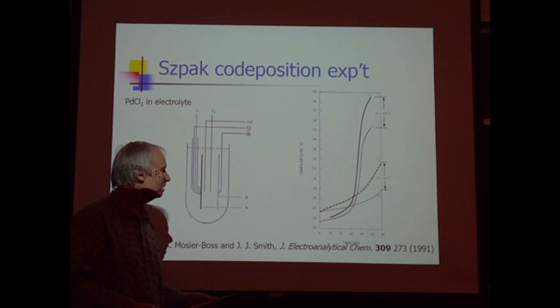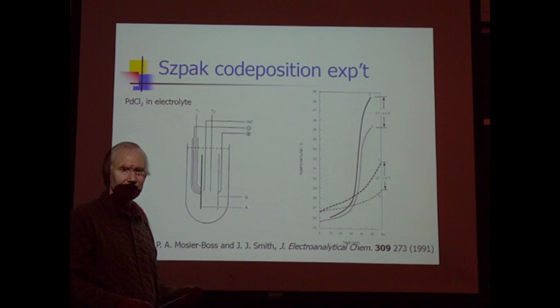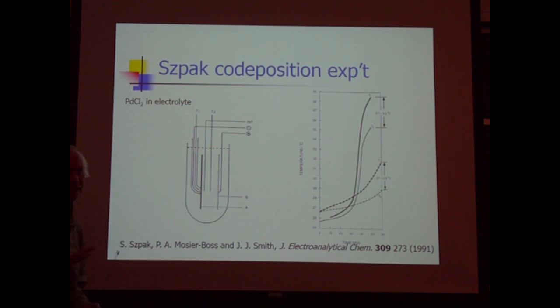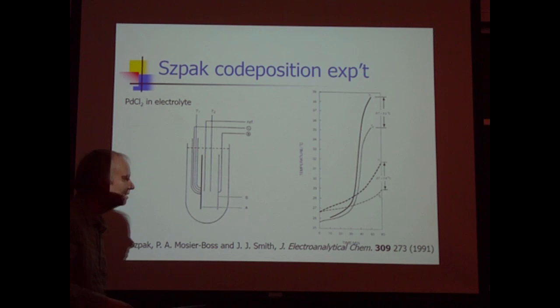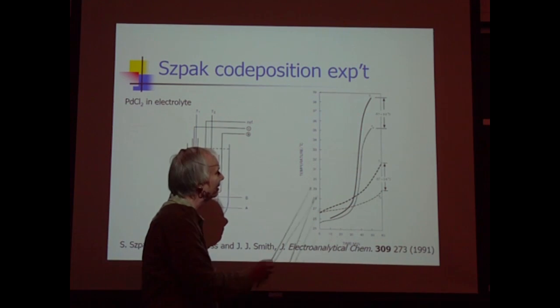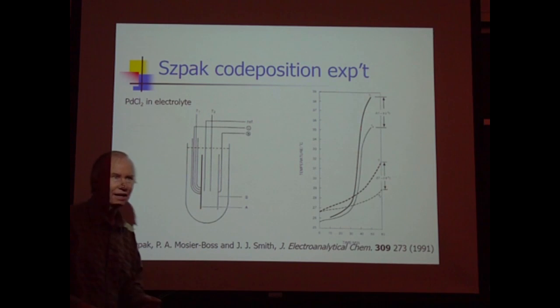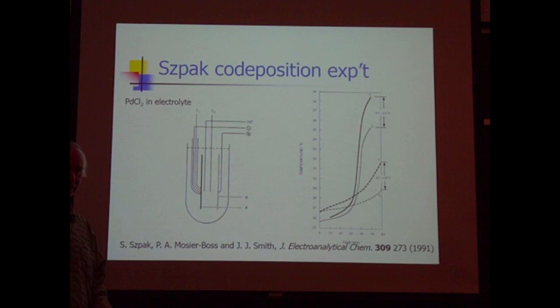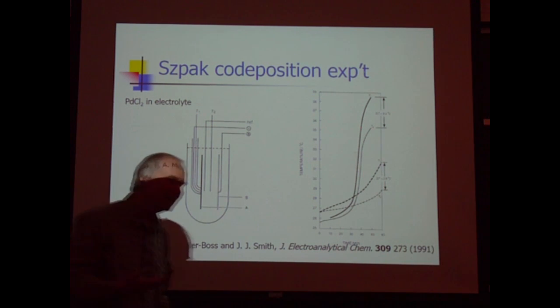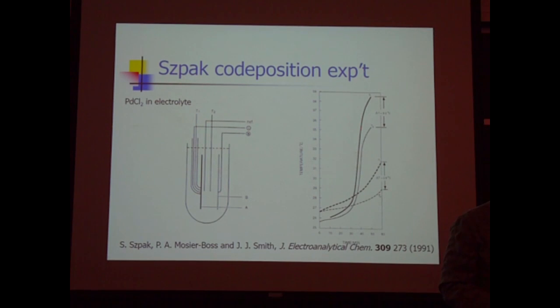However, we remarked on Monday that in the case of Fleischmann and Pons experiments and at the replications at SRI, you had to wait 3 weeks, a month, 6 weeks. You had to load, be gentle with your cathode, eventually raise the current, exercise your cathode. And it took something in the neighborhood of a month before you could see any excess heat. Well, here's Szpak's experiment. Here's time in minutes, here's 0, here's 60, and here's the temperature shooting up following co-deposition of palladium. So in the Szpak experiment, excess heat turns on very quickly. We noted that the diffusion of hydrogen and deuterium into the cathode occurs in a relatively short time compared to the month. So the question is, what's going on during that time?